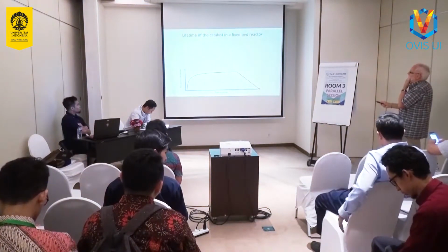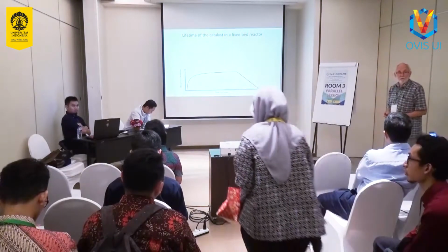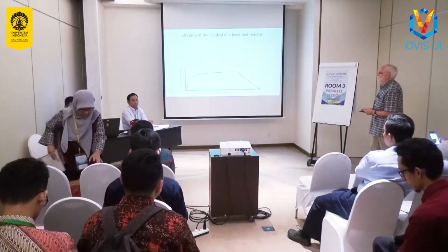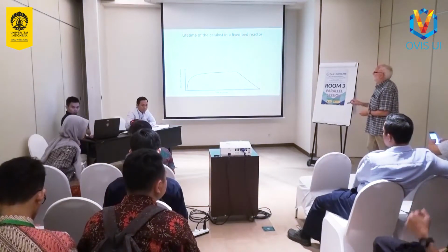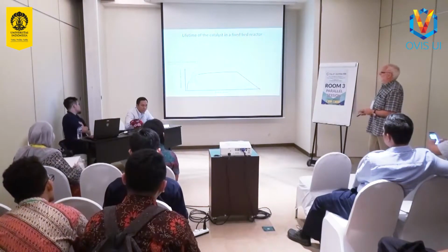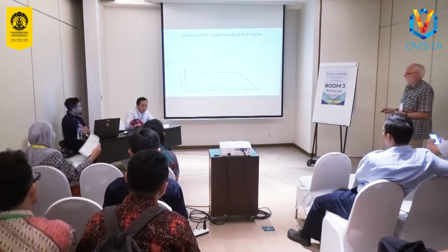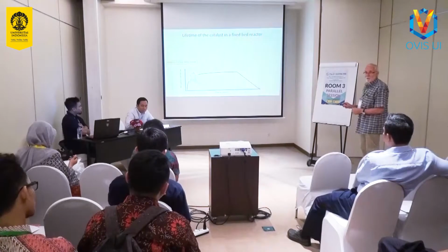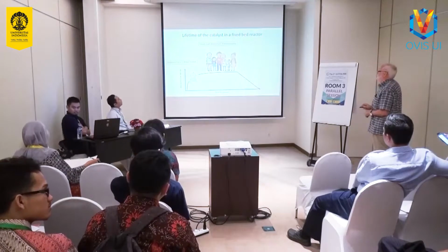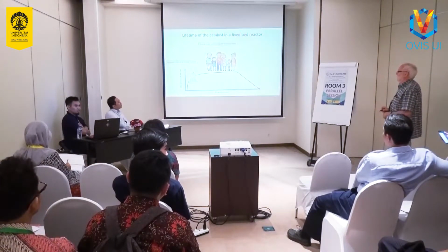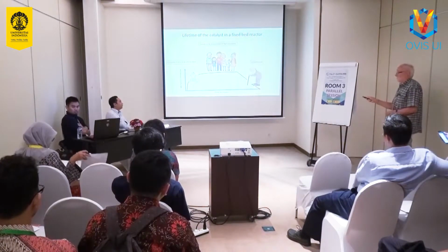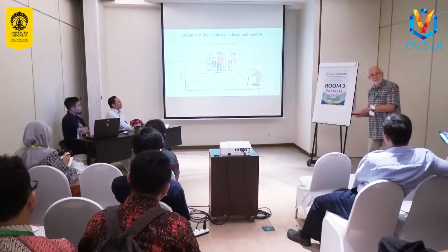Now, if you have this occurring in a fixed bed reactor, which is how we normally do the catalysis, then typically this is what the lifetime profile looks like. There's an initial induction period before the first carbon-carbon bonds are formed. So that's the initiation process for the reaction. Then we get a sort of steady state where the catalyst is converting methanol to gasoline quite happily. Steady state production of hydrocarbons, molecules coming and going, and then eventually the catalyst starts to deactivate, and that's the process that leads to the death of the catalyst eventually.